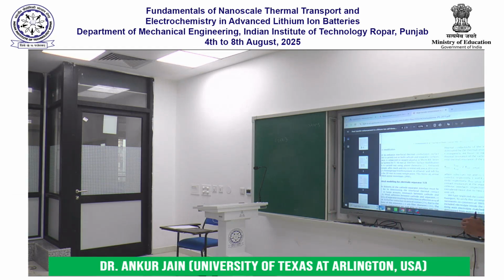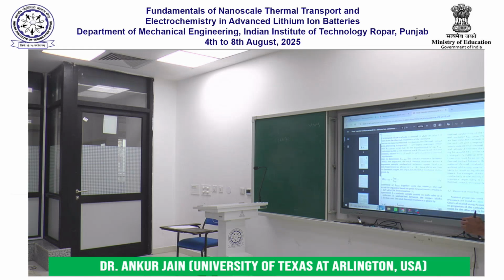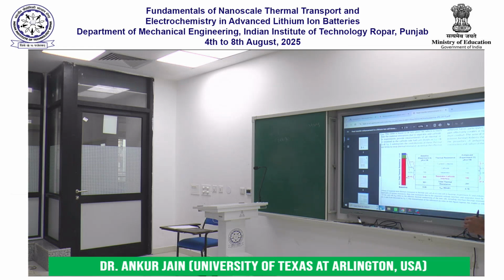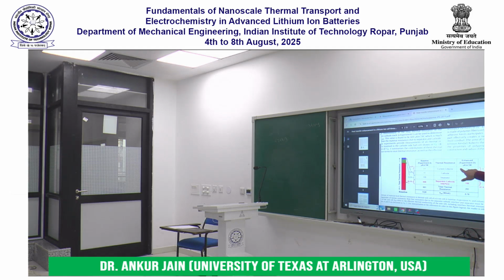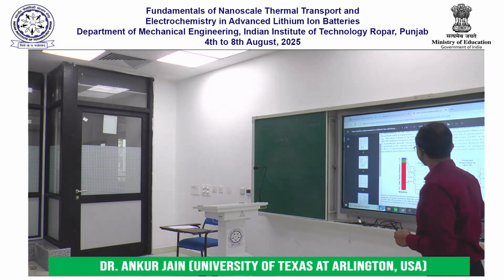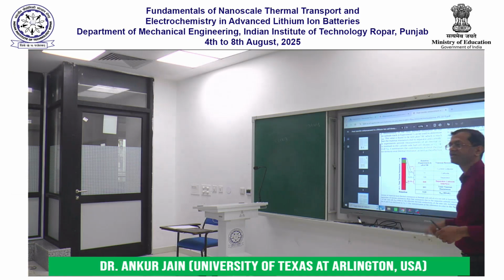if we compare the results of the baseline experiment with the enhanced experiment, you can see here that the first 3 components of thermal resistance don't change, but the interfacial thermal resistance reduces quite dramatically.